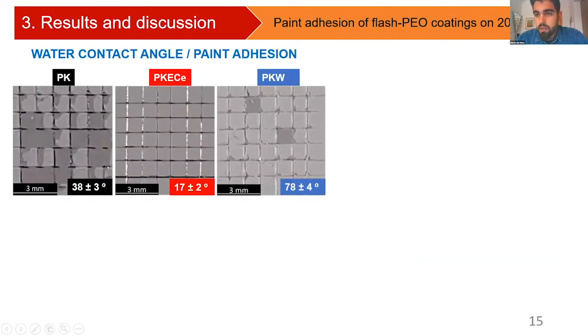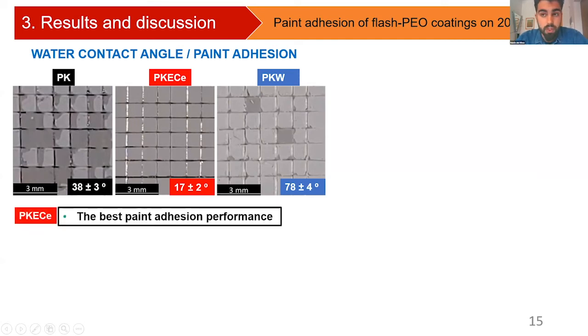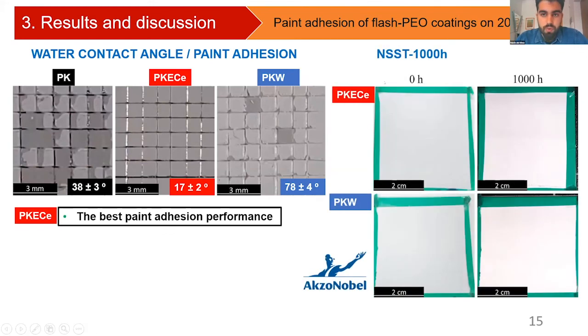Regarding the water contact angle value of these coatings, we confirm that all coatings were hydrophilic. And in the case of the inhibitor-free PEO coating, we achieve very bad paint adhesion. By contrast, for inhibitor-containing PEO coatings, we achieve improved paint adhesion, especially optimal in the case of the cerium-containing flash PEO coating. Then we evaluate the corrosion behavior as a full system with paint by neutral salt spray test